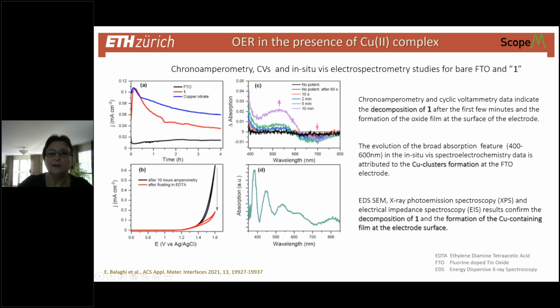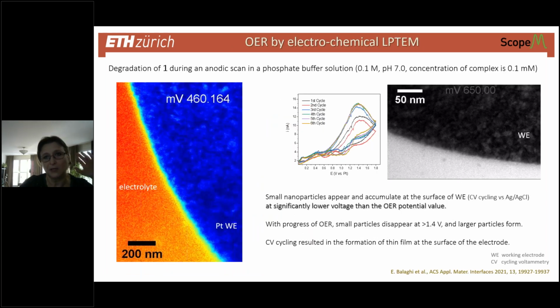Then the in situ visible electrospectrometry study again confirms that this broad feature that evolves within a minute, from about 400 to about 600 nanometer wavelengths, is also attributed to cluster formation at the surface of the electrode. I'm sorry, my mouse is too sensitive. Now, post-reaction study by energy dispersive X-ray spectroscopy in an SEM, X-ray photoemission spectroscopy, XPS, and also electrical impedance spectroscopy confirm that the compound starts to decompose right away after the reaction started, and also confirm the formation of copper-containing species at the electrode surface. This is a very strong and consistent indication, but to know for sure, we went to TEM to verify it, because I have to say it, guys, TEM is the best tool, right?